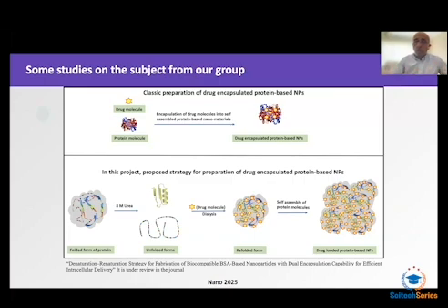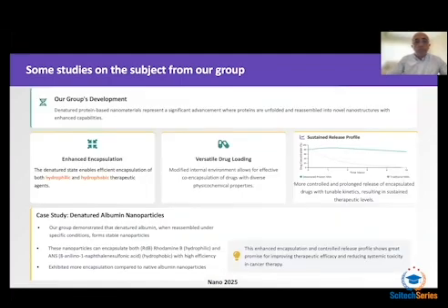The denatured state enables efficient encapsulation of both hydrophilic and hydrophobic molecules, because when you denature protein, hydrophobic and hydrophilic amino acids will be exposed, and they will capture both hydrophilic and hydrophobic molecules for more encapsulation.